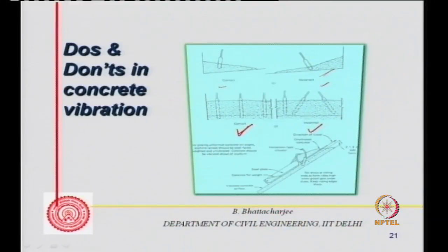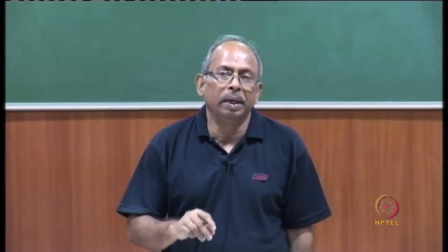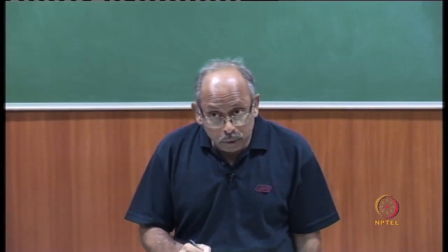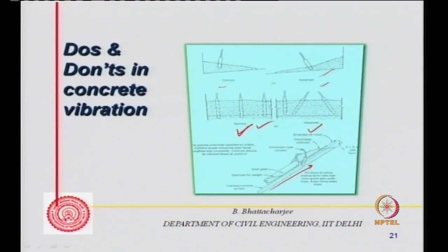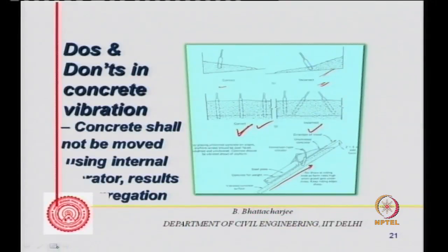And if it is on a slope surface, you place the concrete and vibrate from the bottom and go upward. It is desirable to vibrate vertically downward, without inclining the needle. It is not desirable to incline the needle. And one should not push the concrete by vibration like this being done here. So those are some do's and don'ts with respect to vibration.